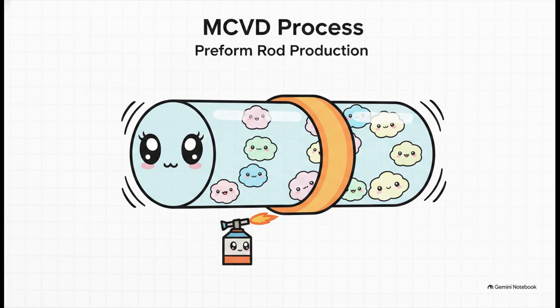Basically, they pass high-purity chemical vapors through a rotating hollow glass tube that's heated by a moving torch. These vapors react and fuse onto the inner wall as layers of ultra-pure glass soot. They also add trace elements like germanium. This germanium slightly raises the refractive index of that inner glass, which, as we'll see in a minute, is absolutely crucial for guiding the light. Once the layers are built up, intense heat collapses the whole tube down into a solid glass rod.